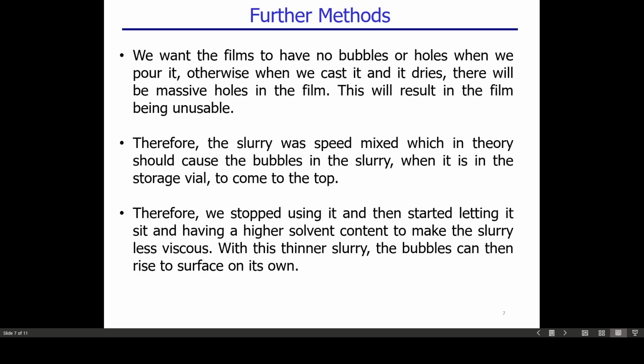Another method that we tried was that we definitely wanted to not have bubbles or holes when we pour it. Therefore, we tried to do something called speed mixing, which is in concept simply like a centrifuge, but just for one of those vials that the slurry was stored in. However, this for some reason just introduced more bubbles in it, so whenever you do cast it, the bubbles would pop and the film would be full of holes, which would render it useless.